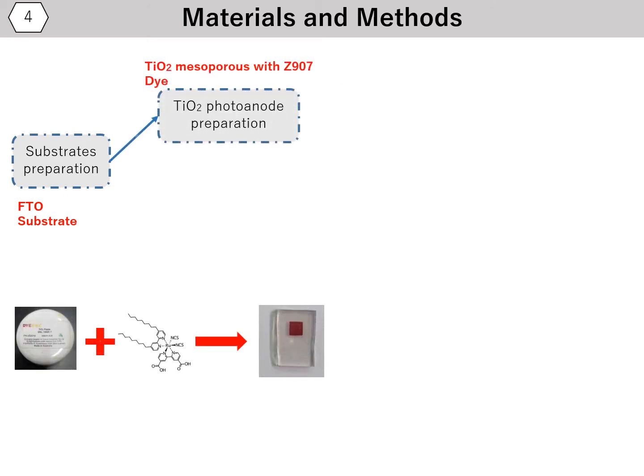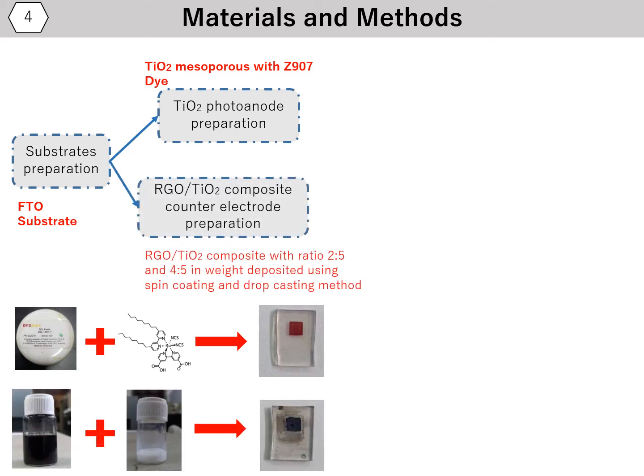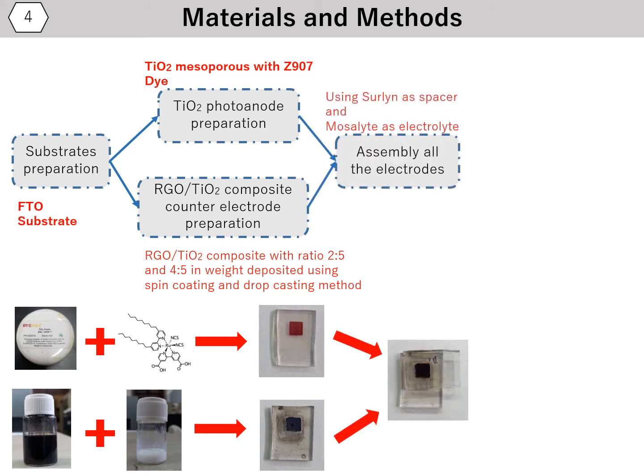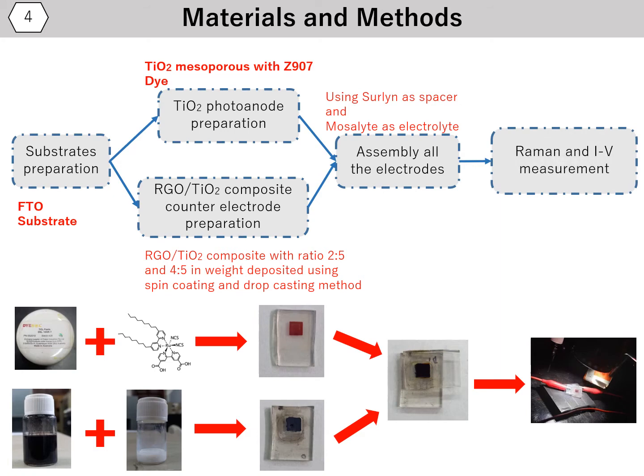For making dye-sensitized solar cell based on RGO titanium dioxide nanocomposite counter electrode, first we prepare clean FTO substrate, then we prepare titanium dioxide mesoporous that is immersed in Z907 dye as photoanode. Then we made RGO titanium dioxide composite with different ratio in weight, which is deposited using spin coating and drop casting method. Lastly, we assemble all the electrodes using surlyn as spacer and Mosalyte as electrolyte, and we characterize the cell using Raman and IV measurement.